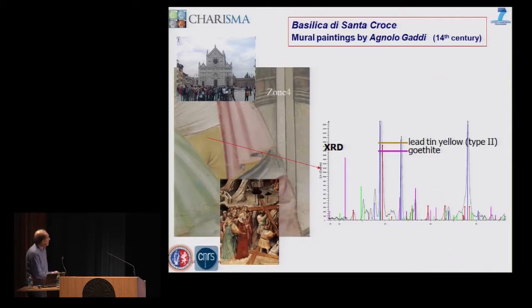But there were other regions where FTIR was blind, and X-ray diffraction gave results indicating the presence of, in these yellow areas, lead-tin yellow type 2 and some goethite. So the integration of the different techniques allowed us to obtain several results that are really satisfactory, because where one technique fails, the other can solve the problem.